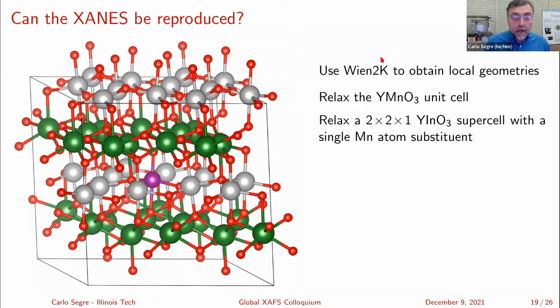So I started by taking the yttrium manganese O3 unit cell and just relaxing it as a single small unit cell. That's pretty fast. Just to make sure I started from a good place. I did the same with the indium, and so I started with something that at least was converged with the Wien2K program. Then I took a 2x2x1 indium O3 supercell, and that's what I'm showing here.